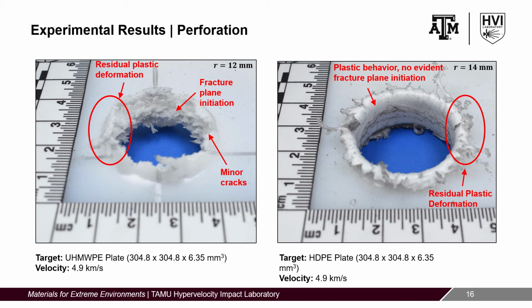Significant residual out-of-plane plastic deformation was observed in both ultra-high molecular weight polyethylene and high-density polyethylene specimens, but more so in high-density polyethylene. The lack of a dominant fracture plane is even more prevalent in the high-density polyethylene specimens, likely due to the impact-induced melting behavior visible in the high-speed images.